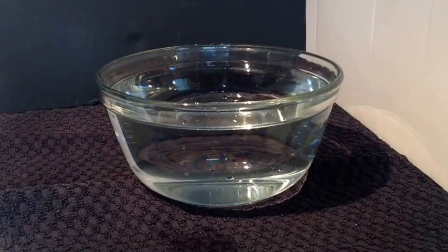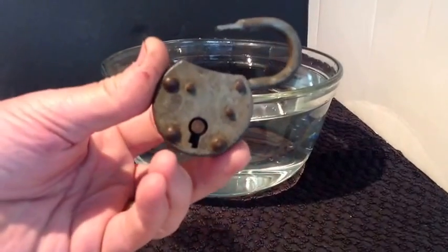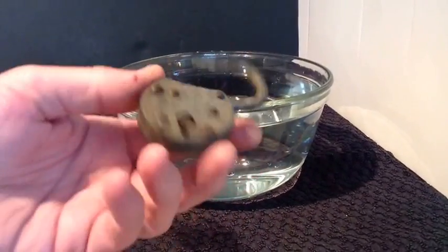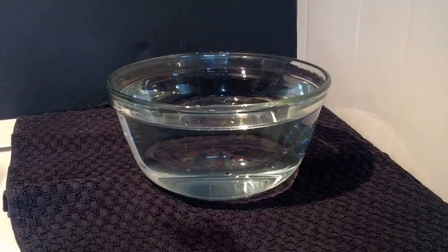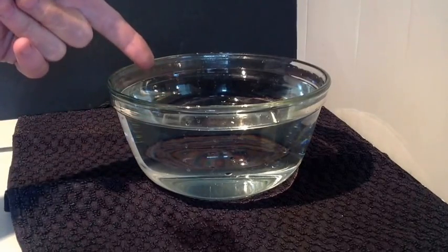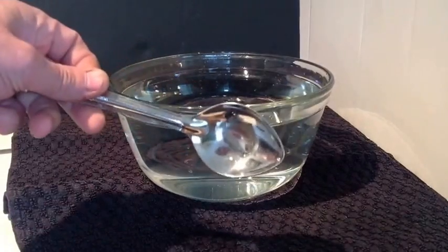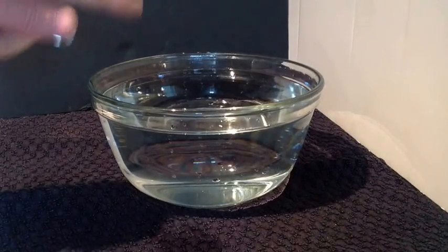What I want to show you today is a process of how to clean up this old lock using electrolysis. Quite easy to do. What we need is a non-metallic dish. I have filled this with 2 litres of water and I have put in 4 spoonfuls of normal salt - just cooking salt. Using warm water because it helps dissolve the salt quicker.